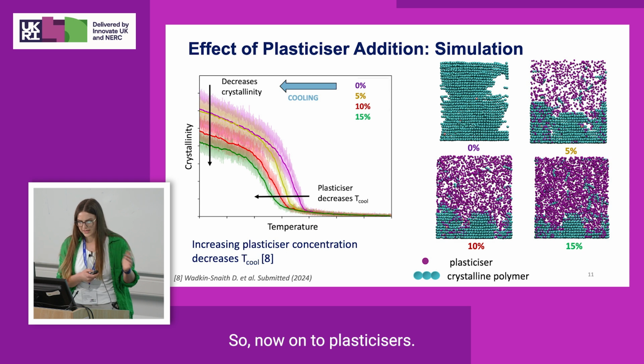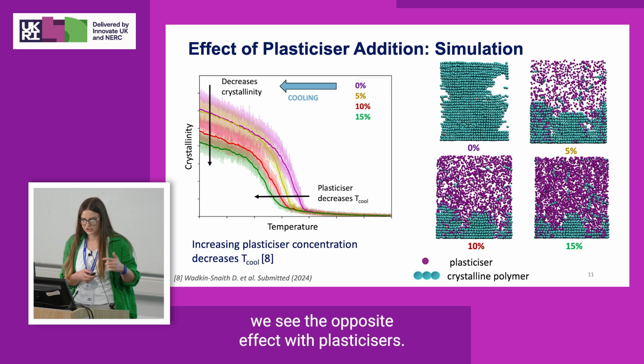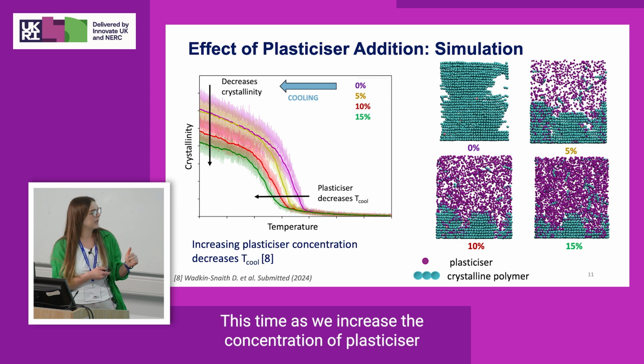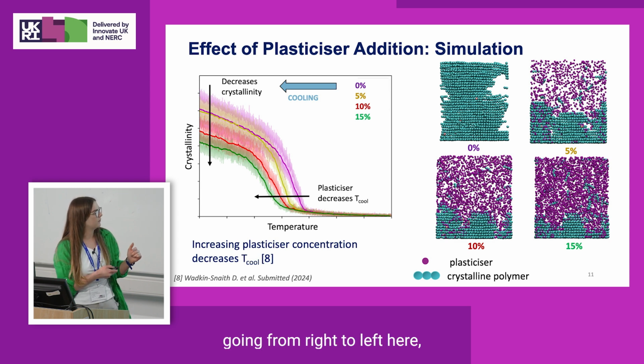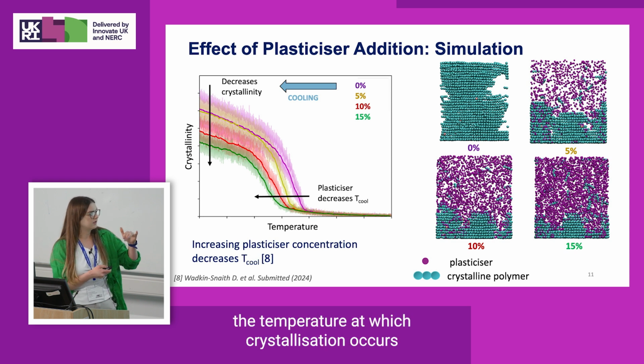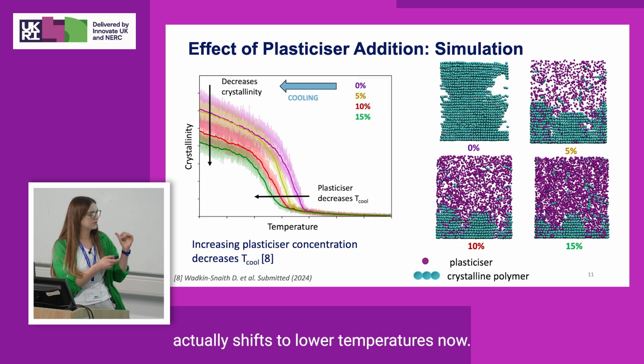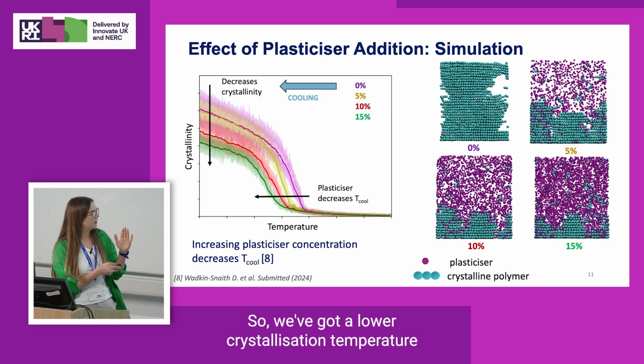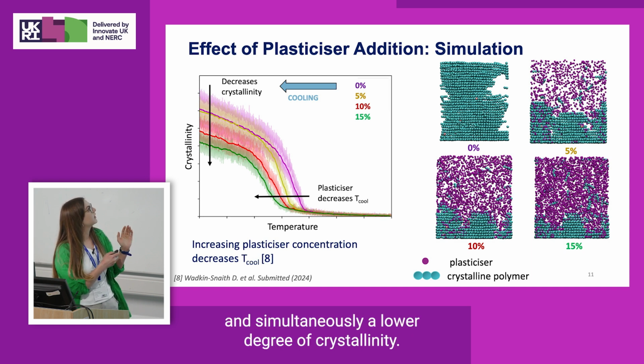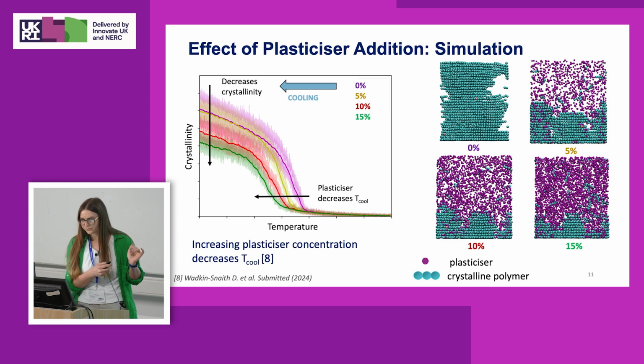So now on to plasticizers. From our simulations, we see the opposite effect with plasticizers. This time, as we increase the concentration of plasticizer, going from right to left here, the temperature at which crystallization occurs actually shifts to lower temperatures now. So we've got a lower crystallization temperature and simultaneously a lower degree of crystallinity.